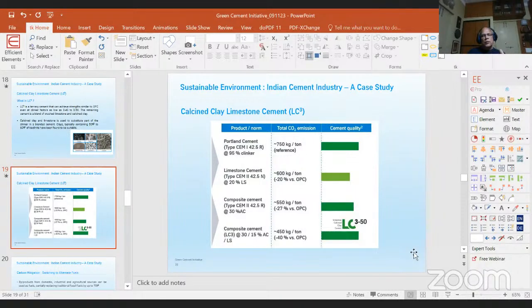If you go with further composite cements of 30% of additive materials, you can come down to 650. But if you go with LC3, you have dramatically come down to 450. So this is a paradigm shift as far as the total CO2 emission is concerned. So that is the technology of the future, I would call it.